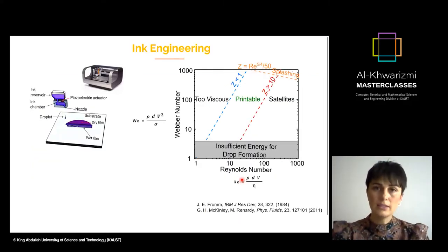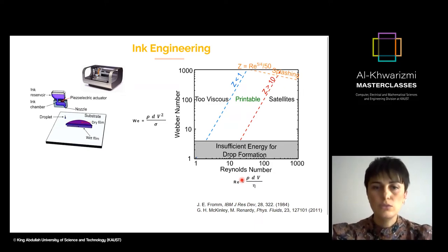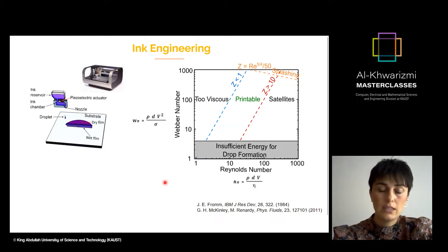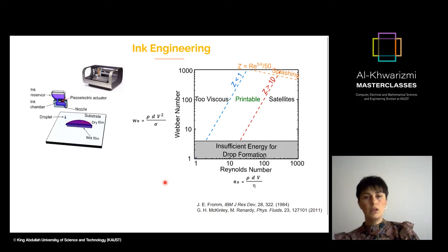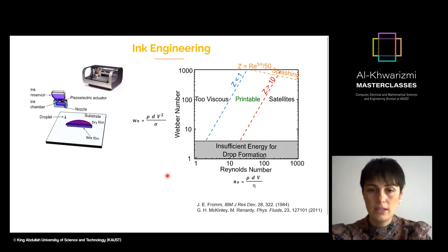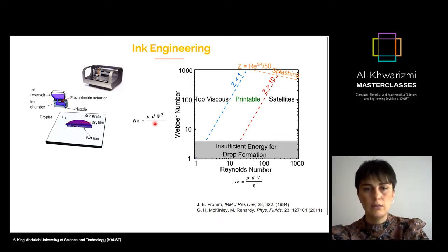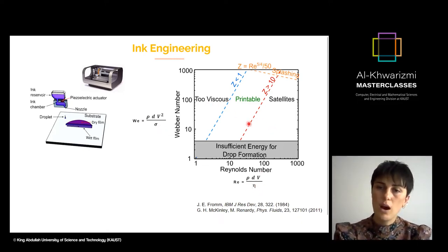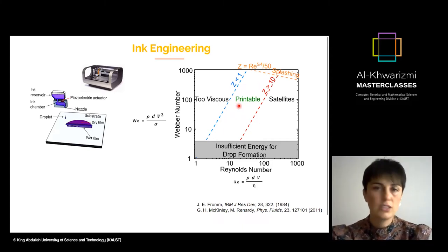And once you have that, you need to think if it's going to be printable. In order to do that, you get the Weber number and the Reynolds number, which consider a couple of important parameters like the viscosity and the surface tension here, which is quite significant for the Weber, and the viscosity for the Reynolds number. You look where you are, and if you're in the printable range, then you say, okay, this ink formulation is good for printability.